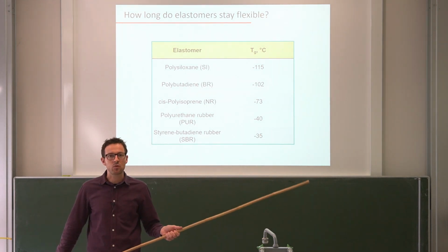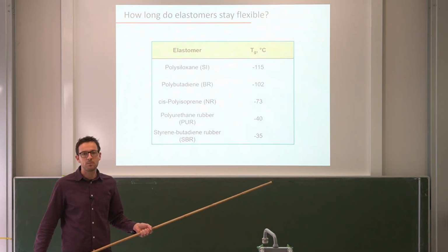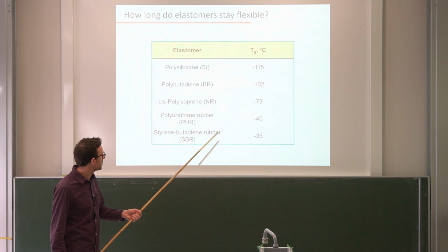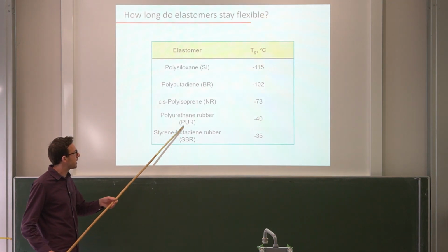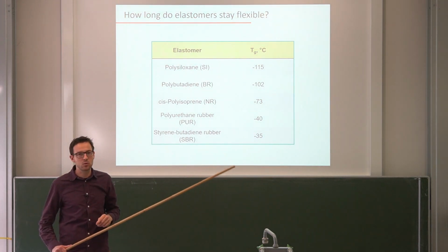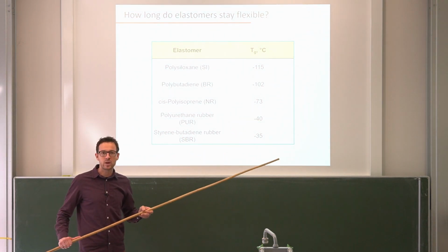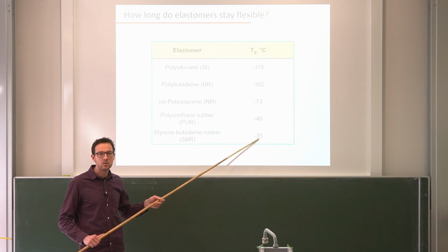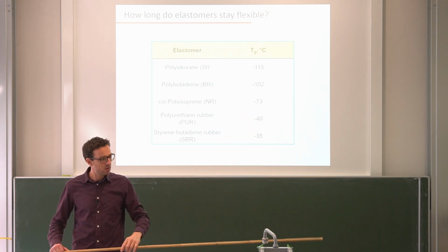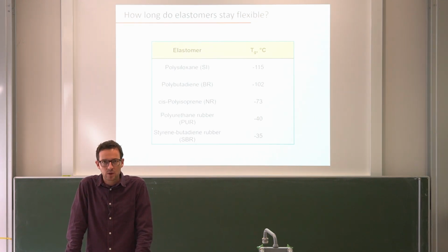That's something we discussed in the very first lecture, that, for example, airplane tires are often made of natural rubber because it has such an extremely low glass transition temperature. And here are synthetic rubbers, polyurethane or styrene butadiene block copolymers. This is the thermoplastic elastomer that we discussed a few weeks ago. And you see that they still behave as a rubber at room temperature, but their rubbery properties fail much earlier compared to natural rubber. Okay, so much for the rubbery state of materials. So we've seen that indeed entropy, well, this is another field of polymers where entropy is really the big player.